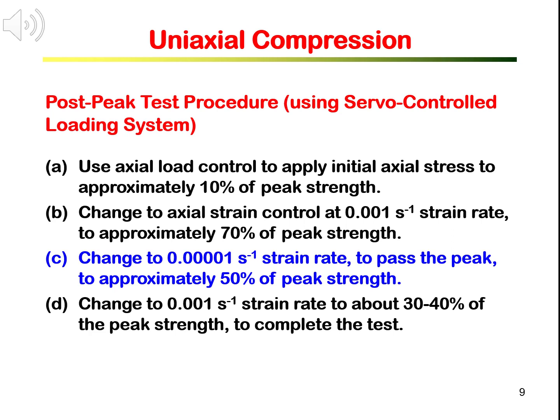The machine will continue to apply loading to the specimen according to the prescribed feedback rate. Let the loading continue to approximately 70% of the peak strength. The rock is now perhaps about to pass the elastic region and start to yield. We then change the feedback axial strain rate to 0.00001 per second, to apply the load slowly and gently to the specimen as it is about to yield, reach the peak, and fail.